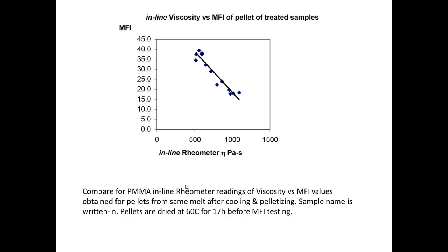a stability which is beyond the reheating in the MFI instrument, which takes 5 minutes or 10 minutes, and then I push the piston to measure, and then it takes another 2 to 3 minutes to make a measurement of MFI. So over at least these 10 minutes, the melt is indeed trying to recover, as we will see, but it's taking such a long time that I am still capable of capturing a viscosity decrease, which was done through orientation within the rheofluidification processors.